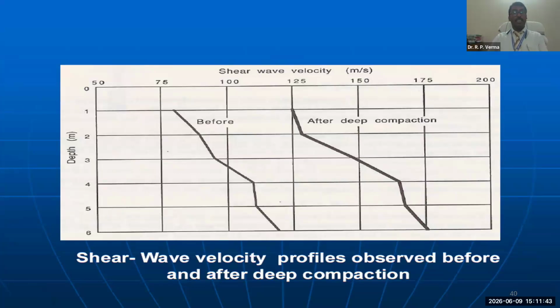This profile illustrates actual shear wave velocity data recorded before and after deep compaction. The baseline curve on the left shows low velocity in this loose soil state. Following deep compaction, the velocity profile shifts significantly to the right, proving an immediate, measurable increase in the shear modulus and structural stiffness of the ground down to 6 meters.